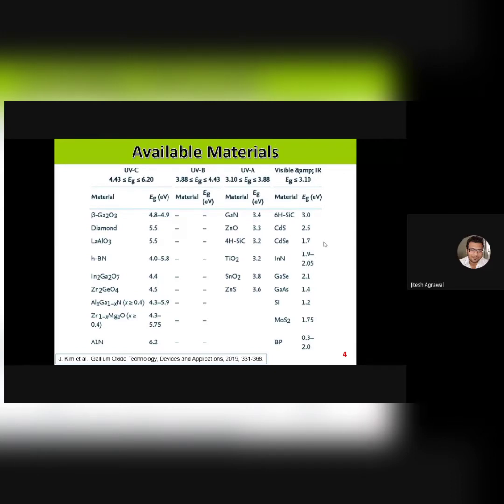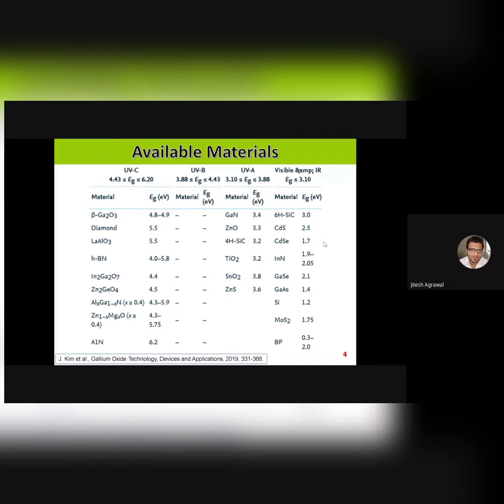For the visible and IR region, there are plenty of materials available, including silicon, cadmium sulfide, gallium arsenide and so on. But if you want to work specifically in the UV region, the majority of materials are metal oxides like zinc oxide, tin oxide, titanium oxide for the UVA region, and for the UVC region there are gallium oxide, indium gallium oxide, zinc germanium oxide, and others. So you have a large range of materials that can be used for UV detection and also for UV emission.